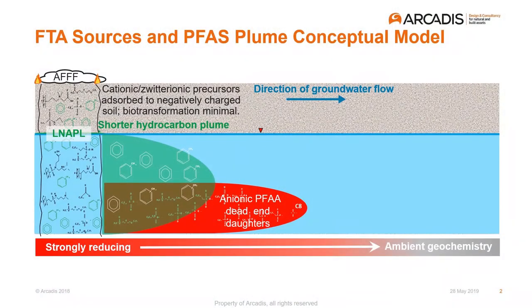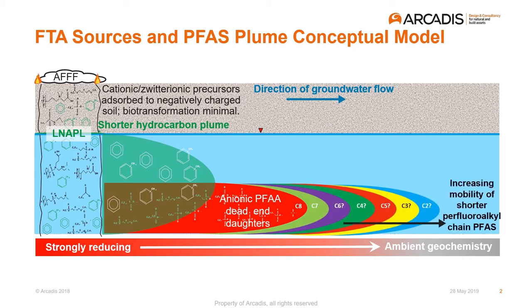If they're cationic or zwitterionic, and you have a high clay content, which has a negative surface charge, you're going to get electrostatic adsorption. It's going to stick around for quite some time. Even though you can get biological transformation of these polyfluoros into perfluoroalkyl acids, the terminal end products that have been referred to as forever chemicals that never degrade, if it's not in the liquid, if it's not accessible to the organisms to do it, they can't do it. So if it's stuck to the soil, this is why we still have PFAS plumes. And some of the data I'll show you is pretty staggering.